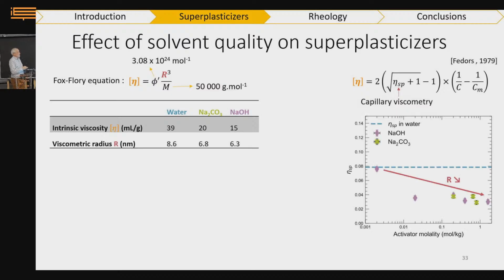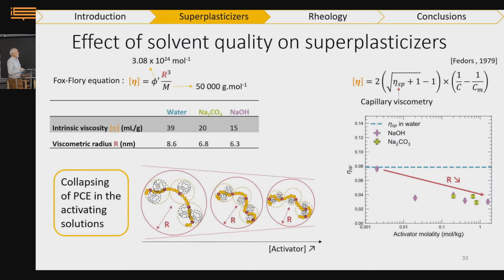So here I plotted the raw data, which is the specific viscosity with respect to the activator molality, and we see indeed the specific viscosity decreasing, and we conclude that the radius has changed. So this is what is schematized here. I have my happy polymer in solution, and then I add salts in it, and it shrinks, it shrinks, progressively. It remains in solution. It's not a phase separation. You are well before the cloud point. So if you look at your solution, it's still transparent, but the conformation has changed.